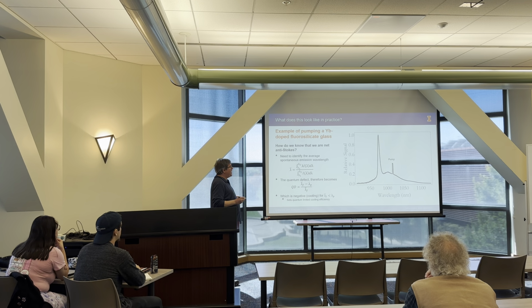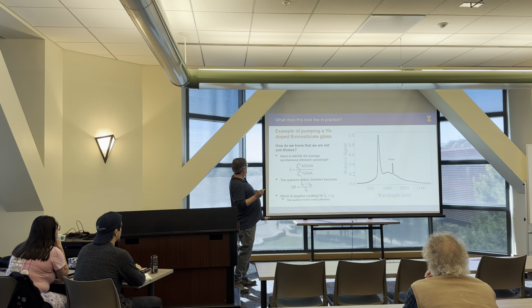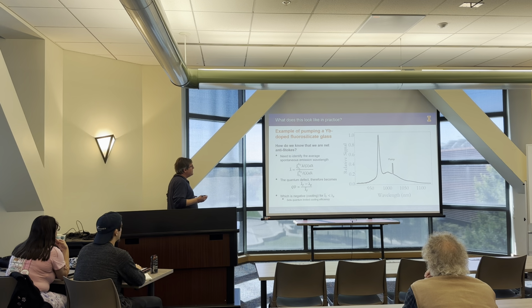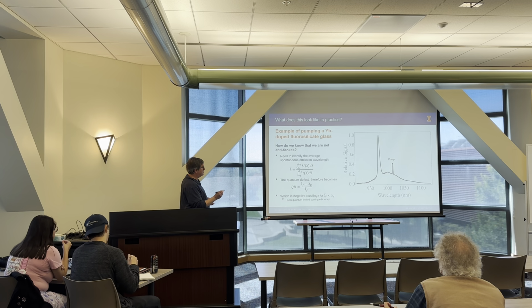So how do we actually quantify whether we're in a state of anti-Stokes fluorescence? Here is an example of some measured data. I believe this is a fluorosilicate glass that we did this with. We were pumping at 1020, and this is the spectrum that we produced. You'll notice that there's a lot of anti-Stokes emission over here. But how much? The first step is to identify the average spontaneous emission wavelength, and that's how we determine an average energy of the system. That's just like taking the average of any function, a weighted average against some value, in this case the wavelength.